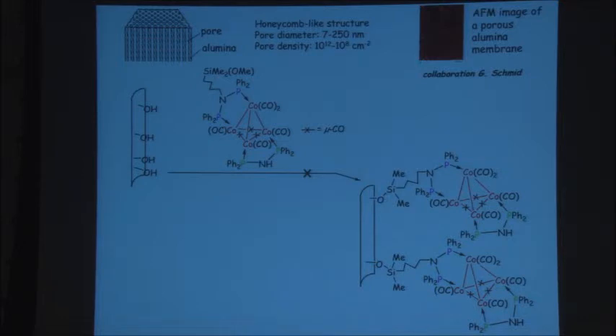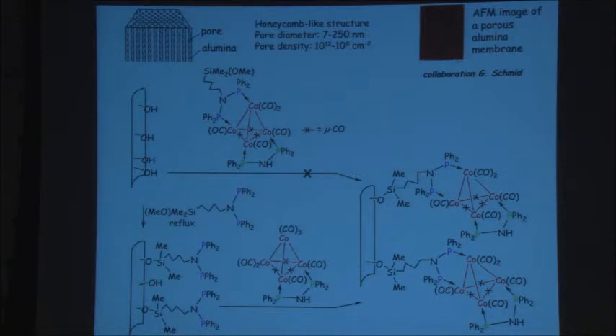Probably our explanation was that this is already a very bulky molecule, and it doesn't enter easily into the channels for steric reasons. So then we did the other approach. We first functionalized the matrix. We have the diphosphine groups here waiting for the cluster to come in.